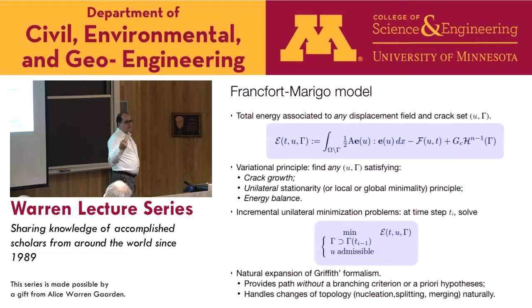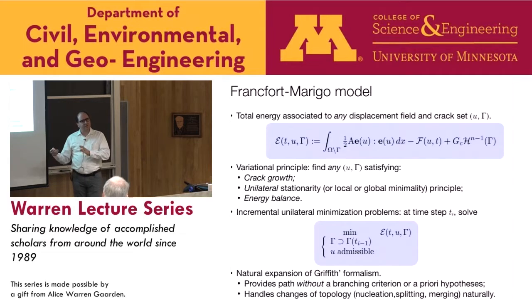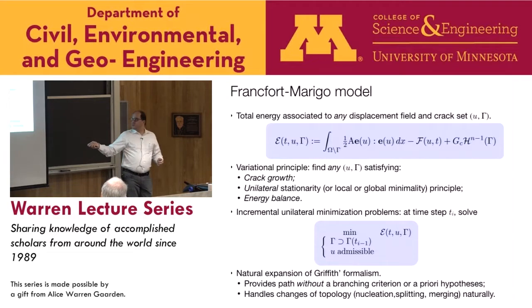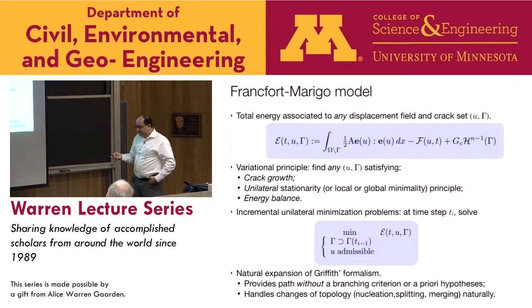And I think that's very interesting because it shows that, modulo 75 years of mathematical development, for the largest part of these 75 years, we always assumed that Griffith's theory was incomplete, that you really needed Griffith's theory for the crack length plus a branching criterion for the crack path. Essentially, what comes from that is that if you take Griffith's idea, growth, stability, and energy balance, it actually is enough information to compute the crack path. It is a complete theory. You just need a more complex setting for the concept of optimization for this type of energy depending on the function and the curve.